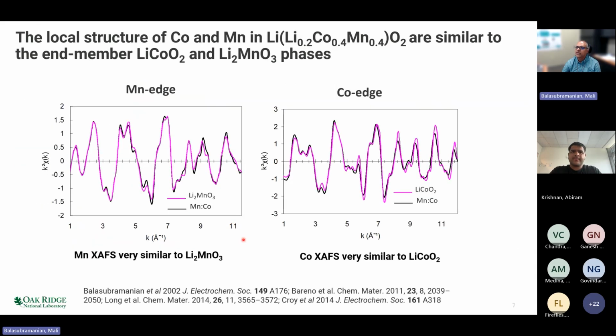And so here is the local structure of a system, which is a solid solution of the end members lithium cobalt oxide and Li2MnO3. And immediately, without doing any processing, just looking at the raw data, you can say that from the manganese viewpoint, the manganese in this compound, the Li 0.2, cobalt 0.4, manganese 0.4 O2, looks very similar to Li2MnO3, but it looks very different from lithium cobalt oxide. Likewise, the cobalt in this compound is similar to that of lithium cobalt oxide. That is, on a local scale, the manganese is similar to Li2MnO3 and the cobalt is very similar to lithium cobalt oxide.